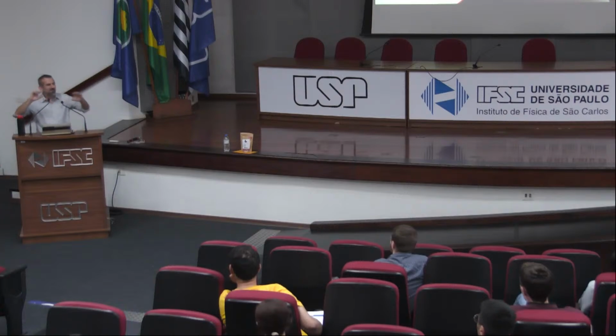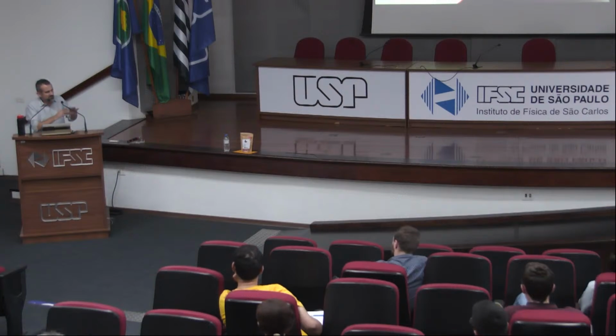So we trained a machine learning potential. We did molecular dynamics of two-dimensional systems. Let's say graphene. Graphene is fancy. And then we want to look for vibrational modes in graphene, in a two-dimensional material. These oscillational modes are very well known. There are oscillations, the G mode, and Raman usually gets this very easily, okay? We can get this from ab initio calculations very easily. However, there are some very slow modes on 2D materials that are related to long wavelength ripples. You imagine there are some very long wavelength waves on the material that distort this material. There are some beautiful pictures that show graphene oscillating, right?